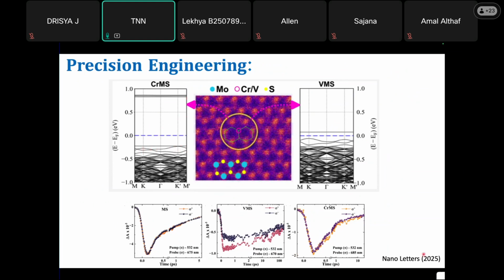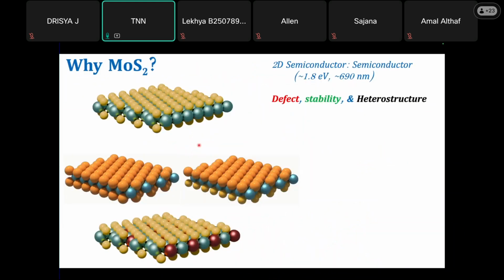And in recent work, we found that you can control the valleys by choosing the right transition metal, replacing the position of Mo in a very small amount, and that way you can engineer the valleys. So the electronic properties brought by chromium and vanadium are similar, but the valleytronics parts are different. So this is quite nice. You can engineer the electronics independently, valleytronics independently, etc. It's bringing a lot of opportunities to use this material for beyond electronics too.